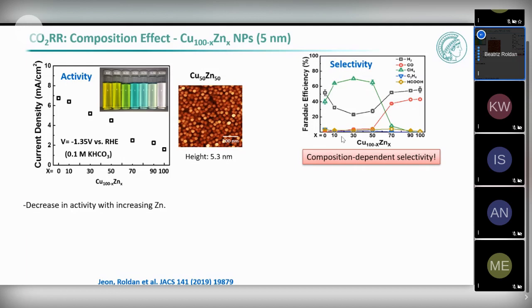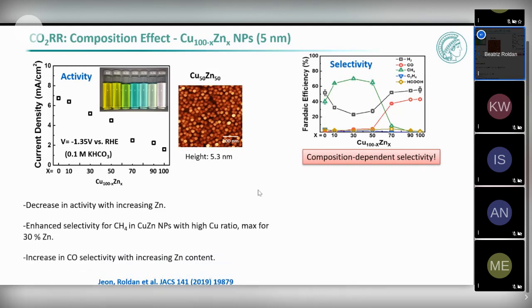If we look at the composition, we can see a very interesting trend. So with increasing zinc content, we see that again we favor the production of CO, and this is here also hydrogen that we are producing. But if you are in a concentration here between 10 and 50% zinc in these copper zinc nanoparticles, we favor the production of methane. So what we learned is that for these small nanoparticles, there is a clear change in the selectivity when you change the content of zinc in these copper zinc nanoparticles.